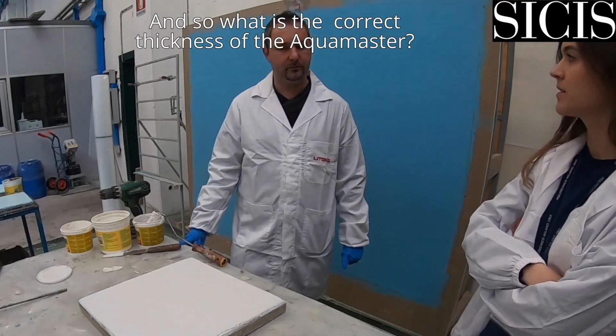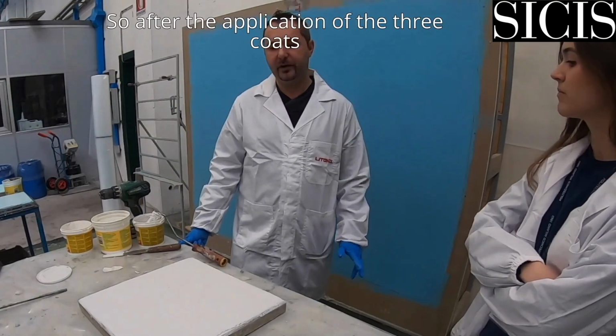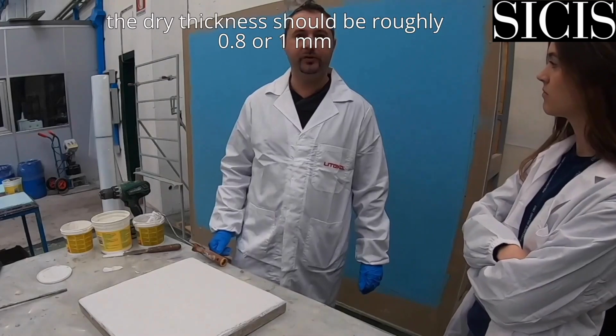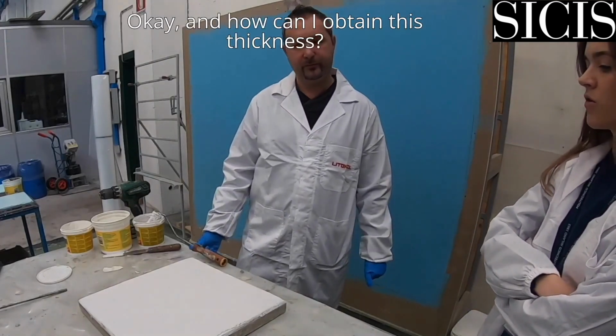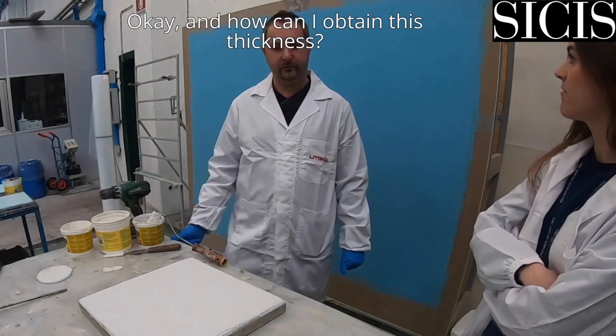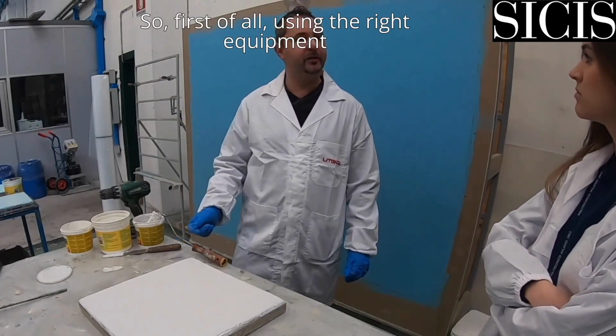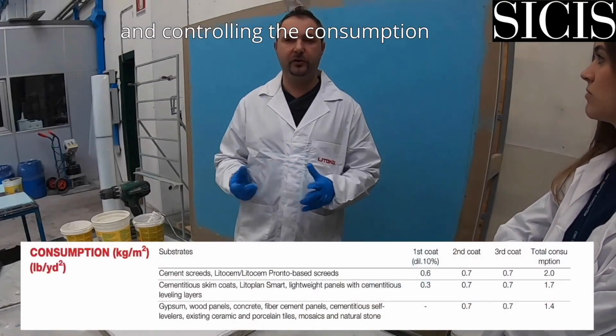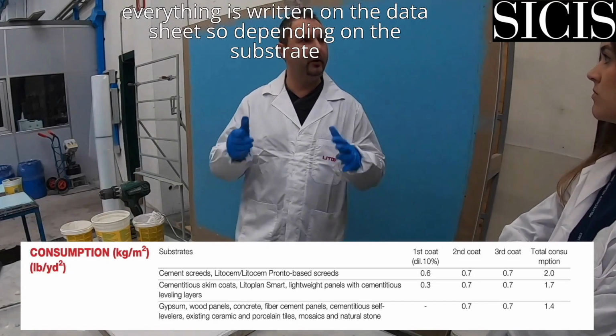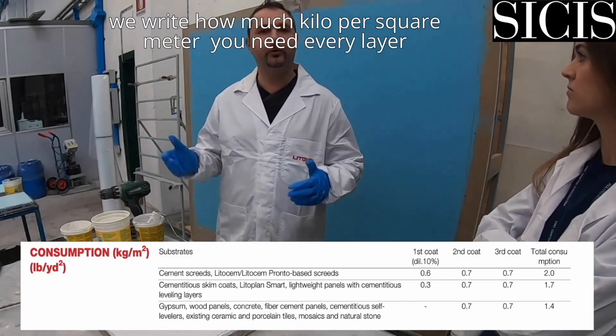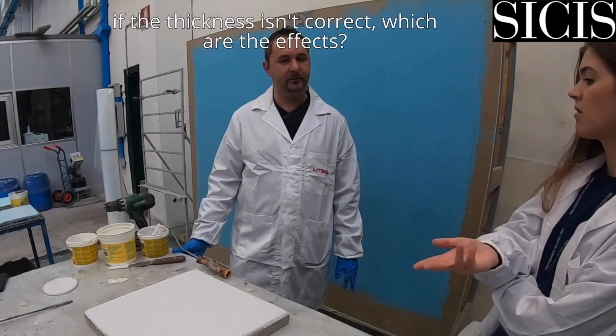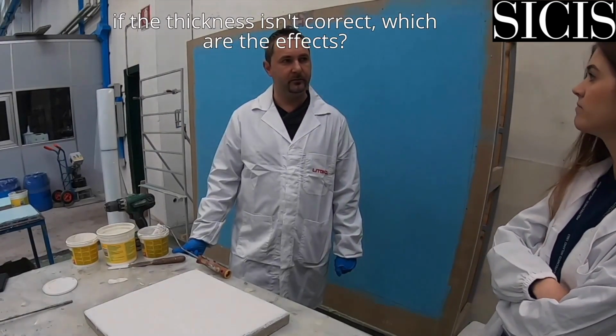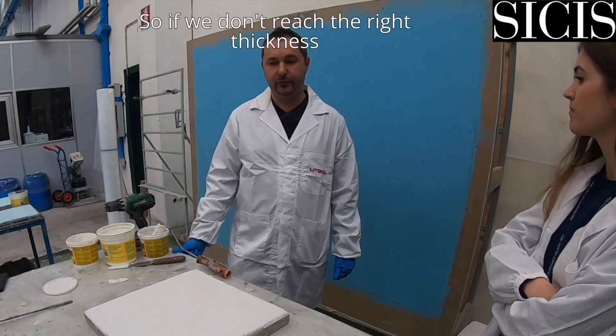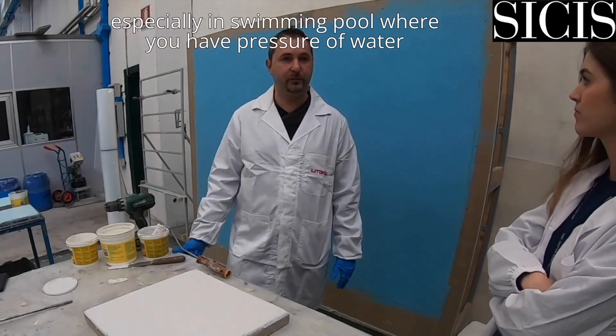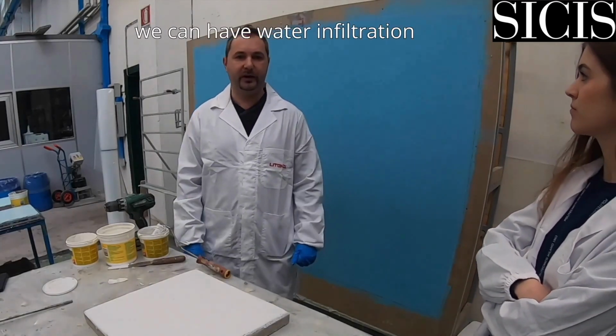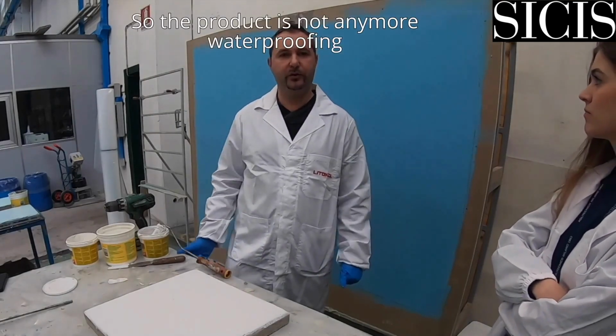What is the correct thickness of the Aquamaster? After the application of the 3 coats, the dry thickness should be roughly 0.8 to 1 millimeter. Okay, and how can I obtain this thickness? First of all, using the right equipment, a roller with long peels, and controlling the consumption. Everything is written on the data sheet: depending on the substrate, we write how many kilos per square meter you need for every layer. If the thickness isn't correct, what are the effects? If we don't reach the right thickness, especially in a swimming pool where you have pressure of water, we can have water infiltration, so the product is no longer waterproofing.